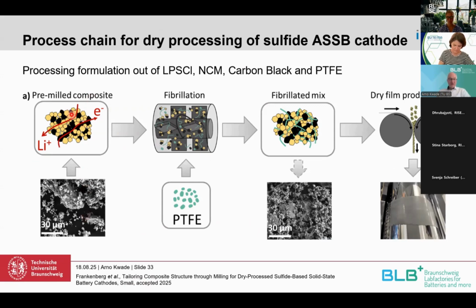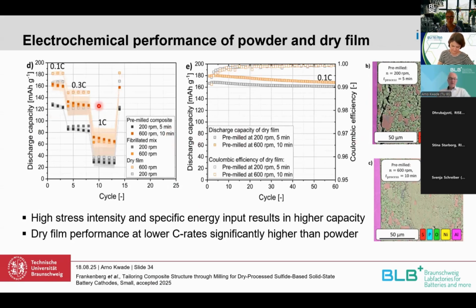We have this process chain: a pre-milled composite, then a fibrillation of the PTFE binder, then the fibrillated mix, and the dry film production. And if we look into the results, we see that even if we compare the powder, which is only normally processed or compressed, with the cathodes we produce by this dry film formation, we have an increase in performance due to this film formation using the calendering machine. And we are almost getting the reference capacity of our material, forming this dry film for this solid state battery cathode. And this is really nice to see.